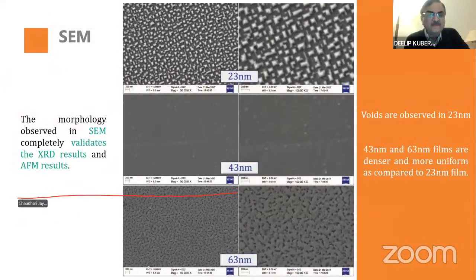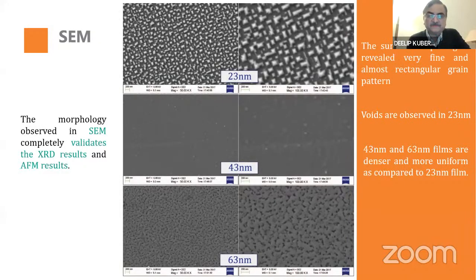Okay, then these are the SEM images. This is grain morphology studied using the SEM, and these SEM studies validate the XRD results and the AFM results. In the 23 nanometer films, we have got some voids observed, whereas in the 43 and 63 nanometer films, we have got a uniform structure as compared to the lower thickness films.